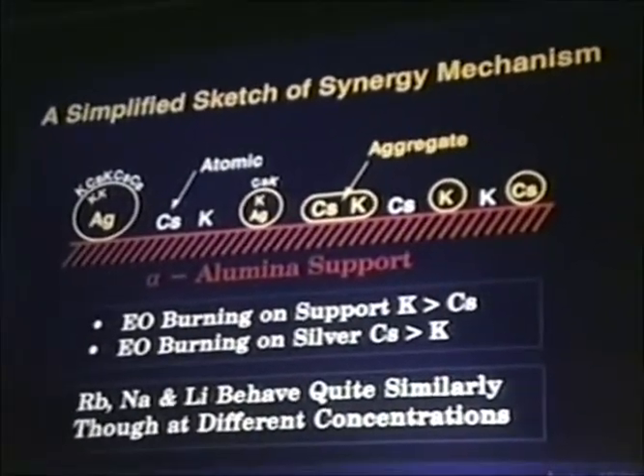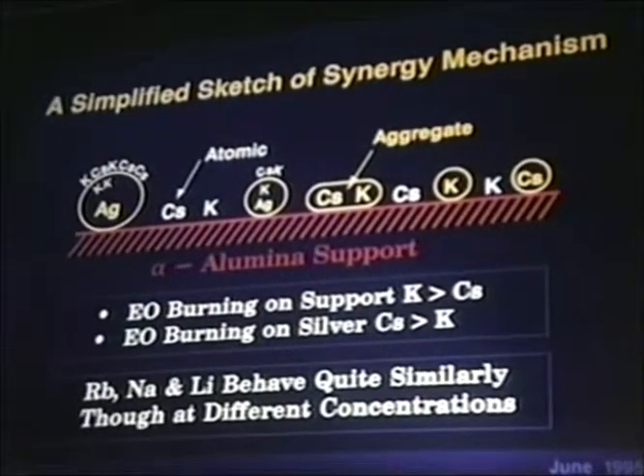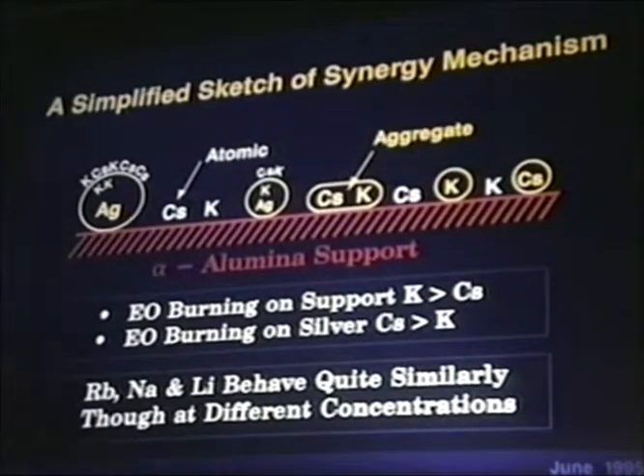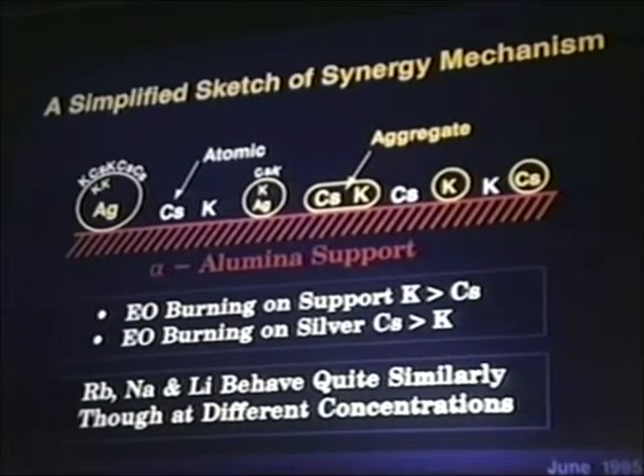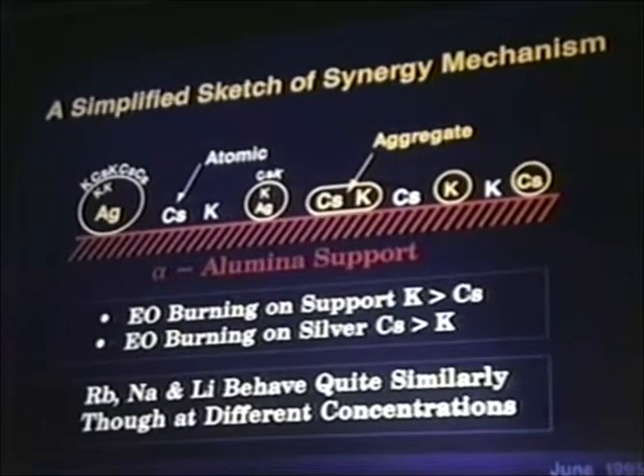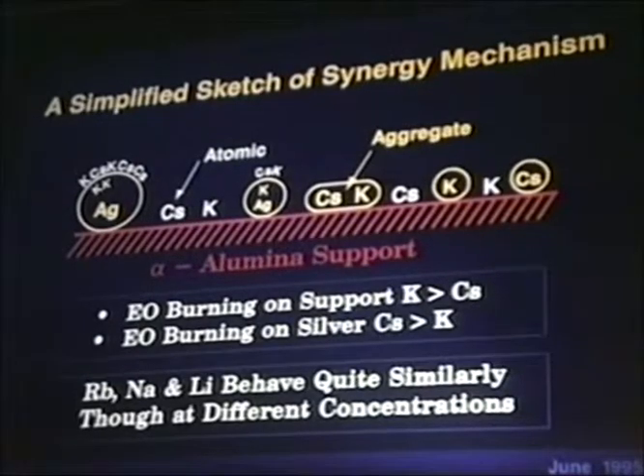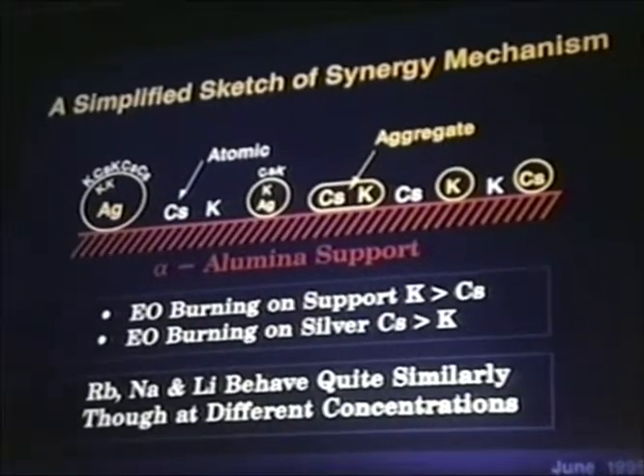In the next slide, I have a pictorial demonstration of an alpha alumina support on which you have silver and cesium and potassium promoters. It's certainly a simplified sketch, but I certainly beat showing you 10 slides. I'm sure you can all appreciate that. We don't want to be here past coffee hour. In this simplified sketch, you can see that cesium and potassium can be on the silver surface and they can be on the support surface as they are manufactured and put together.